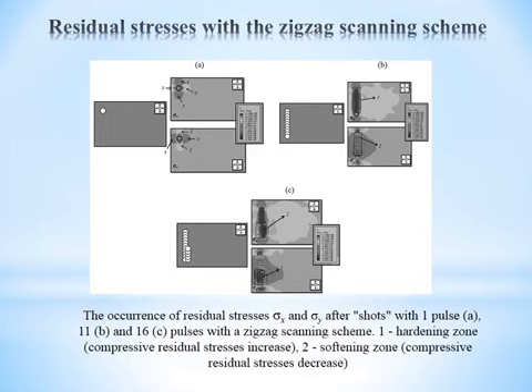Inside the laser shot, the residual stresses sigma x and sigma y are almost the same. However, outside of the spot, their values differ significantly from each other. Namely, for sigma x, the compressive residual stresses, CRS, occur in the upper and lower regions of the laser shot, and the tensile residual stresses, TRS, occur in the left and right regions of the spot. For sigma y, we have the opposite picture. The CRS occurs in the left and right parts of the spot, and the TRS occurs in the upper and lower regions. The residual stresses that occur in this case are the same in absolute value but have different signs.